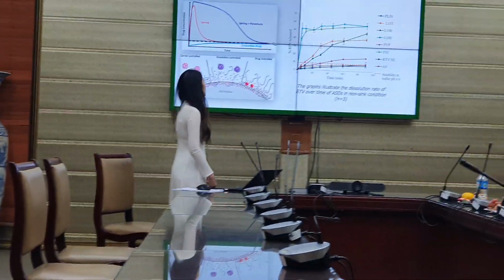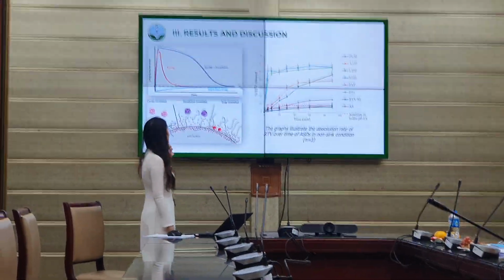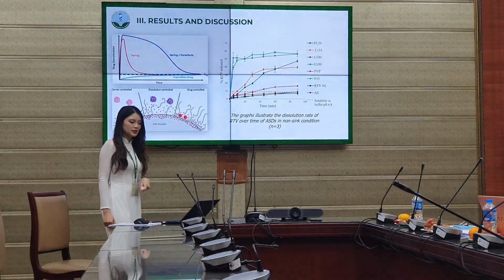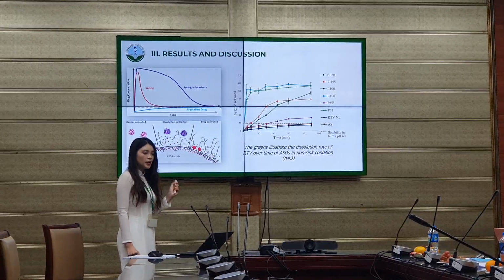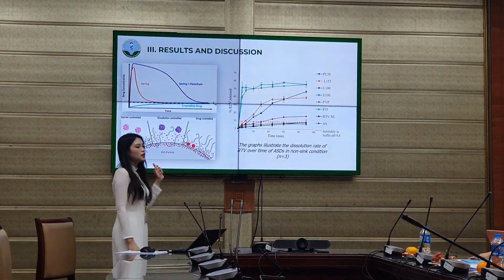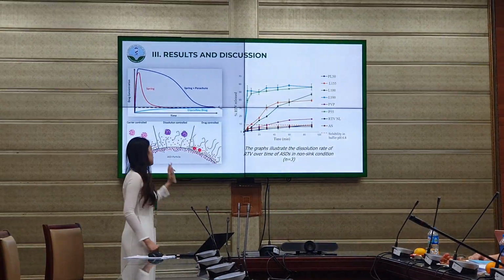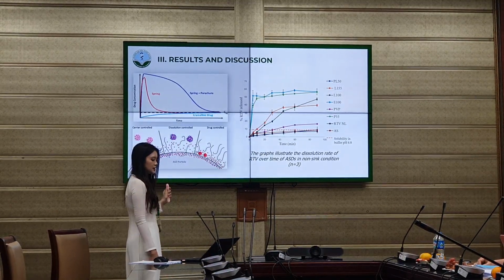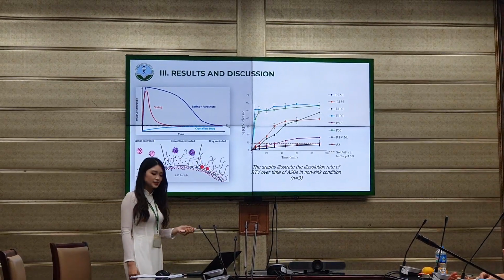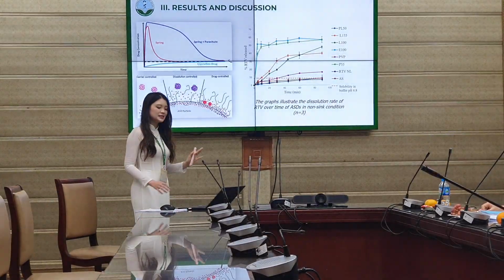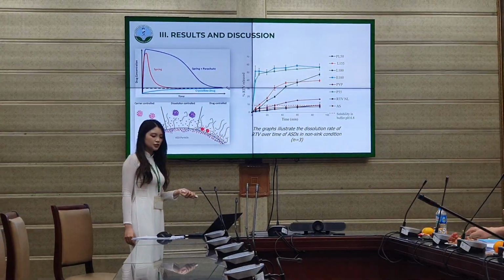And the graph illustrates the dissolution behavior of different drug formulations, particularly highlighting the spring and parachute phenomena, often observed in the amorphous solid dispersion. So the spring refers to the rapid initial increase in drug concentration, but unstable, leading to recrystallization and a sharp decrease in the concentration. The parachute describes the system's ability to maintain supersaturation over time, typically due to the presence of polymer or excipients that inhibit the recrystallization.